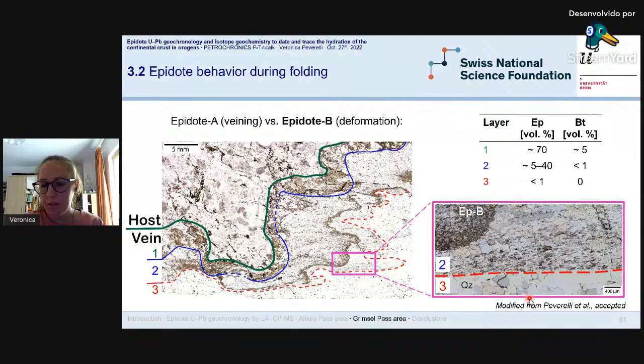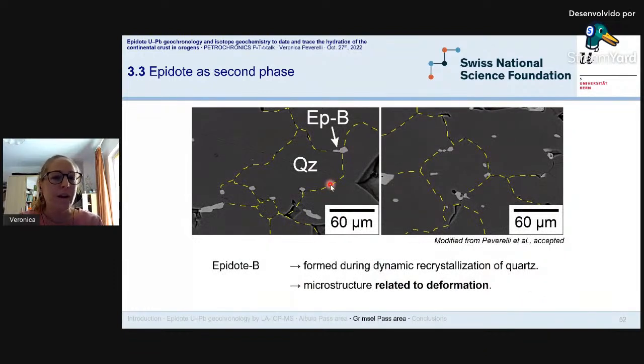If you look closely here, you will notice that where epidote is most abundant, and we're talking about epidote B now, quartz has the smallest grain sizes. Where epidote is basically absent, quartz is much larger, and it reaches its maximum grain sizes. We also find anhedral epidote B grains measuring up to about 15 microns. We find them along quartz grain boundaries. So these grain boundaries formed during dynamic recrystallization of quartz. They are the result of the response of quartz to deformation.